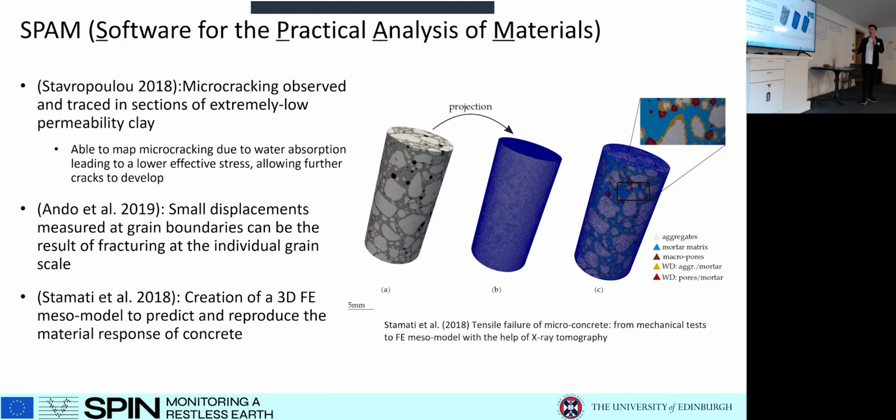And the next one is maybe a little bit ambitious for the project, but there's an example done by Stamati, and they were able to take their 3D tomographies and convert these to finite element meshes, and then accurately predict and reproduce the material response of concrete samples that they had. So they were able to predict tensile failure.